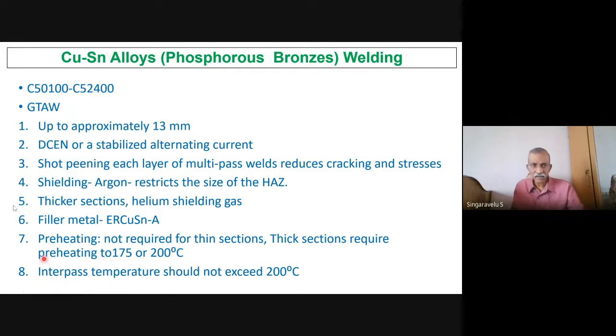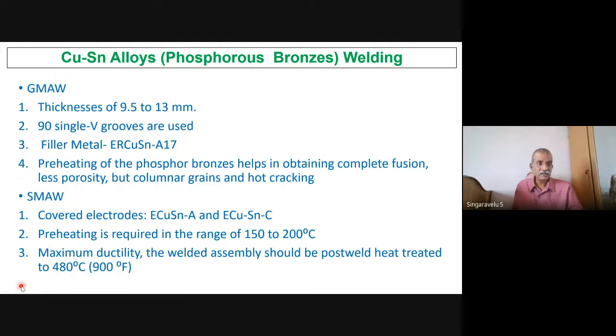Coming to the phosphor bronze, in the case of TIG, up to 13 mm you can do DCEN or a stabilized alternating current. Each layer has to be shot peened, that's very much important. Shielding gas is argon. For thicker sections, go for helium. Then only you can get the penetration we have shown. Filler is ERCUSN-A. Preheating for thin sections is not required. Thick sections call for 175 to 200 degrees centigrade. Caution: 200 degrees is the interpass limit. Do preheating, do welding, stop, do welding like that. This is the technique, right?